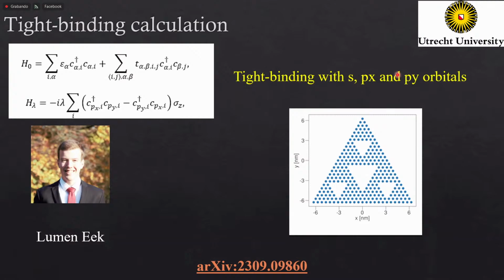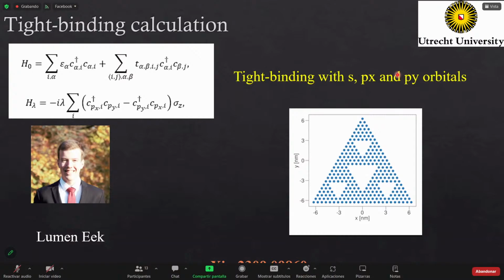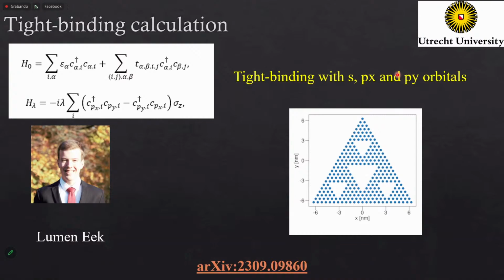But since there are no ab initio calculations for this specific material, we took the ones from bismuth and just changed them a bit, because our idea is not really to do ab initio modeling of that. And as I mentioned, in terms of the energy levels, they're not really correct. But we just wanted to do a kind of minimal model for the system to understand it. So the specific terms we use from the cluster, but the values themselves we chose as the ones closer to the experimental results. So it was a kind of fitting. It was not really ab initio.